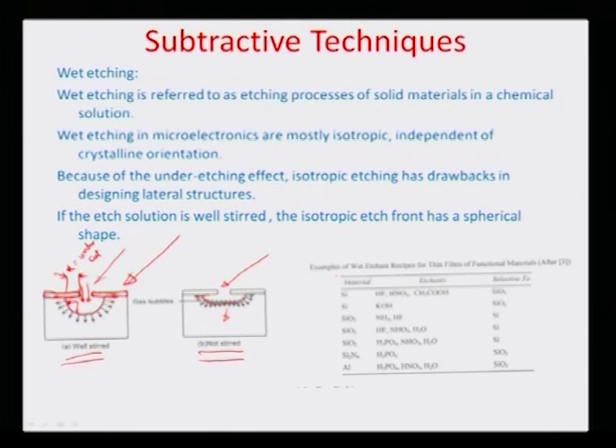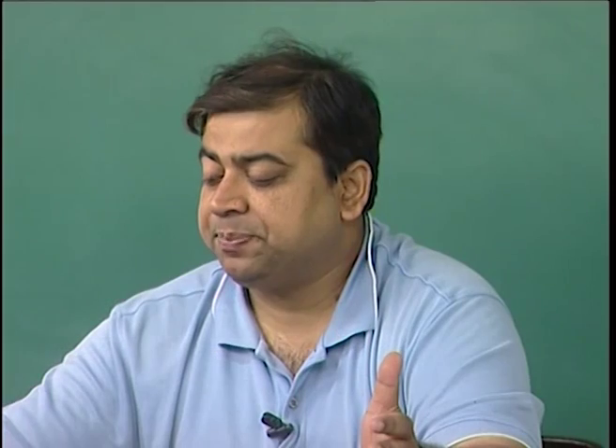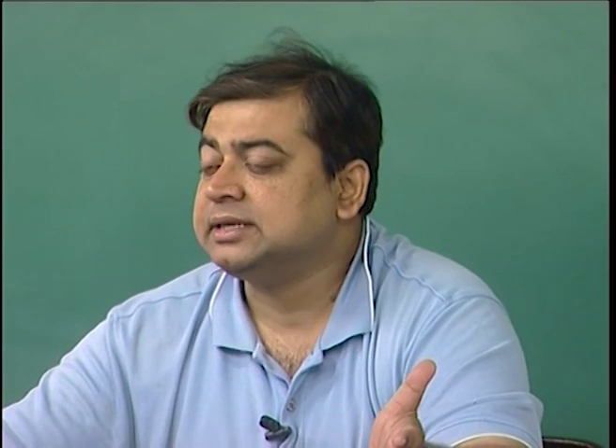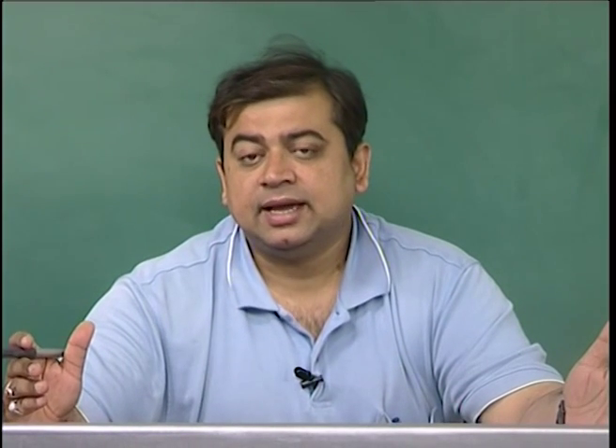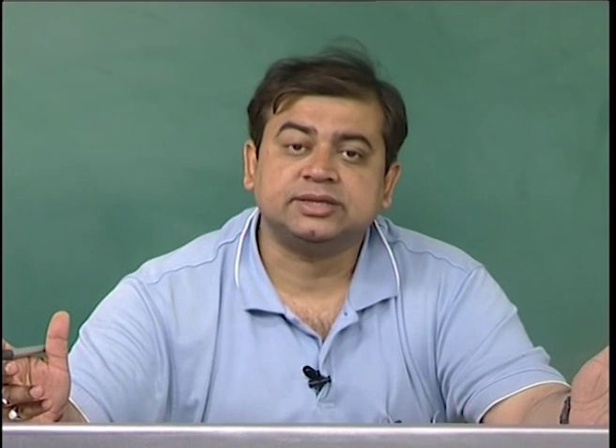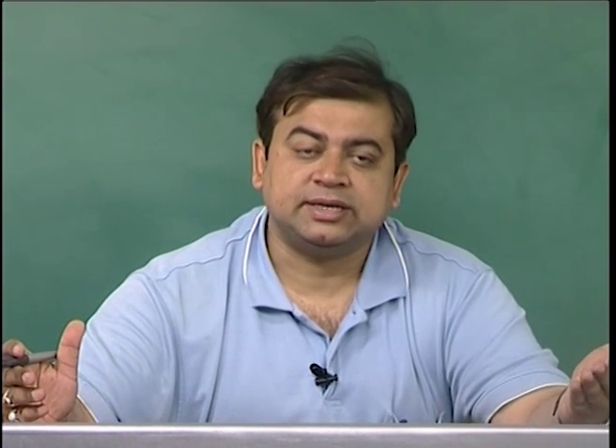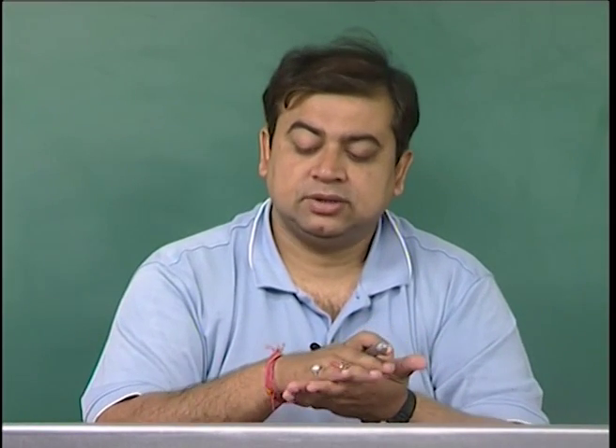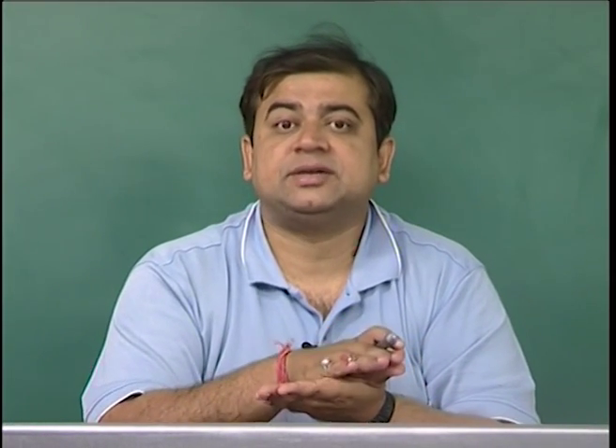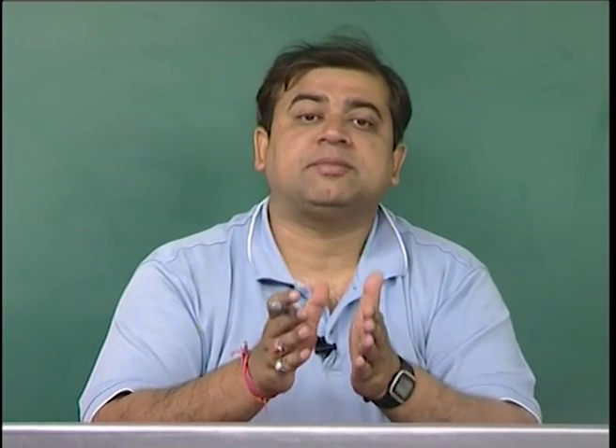Let's look at some of these materials and the etchants which are used for them and what they are selective to. Etch selectivity is a term used in reference to the fact that there are certain materials which may not get etched away by the etchant solution. In that case, this material which is not affected by the etchant solution can be used as a protective layer to stop the etching process very accurately. Therefore, an etch stop layer, or an etch selective layer, is always preferred as the layer which would prevent the etching from happening any further.